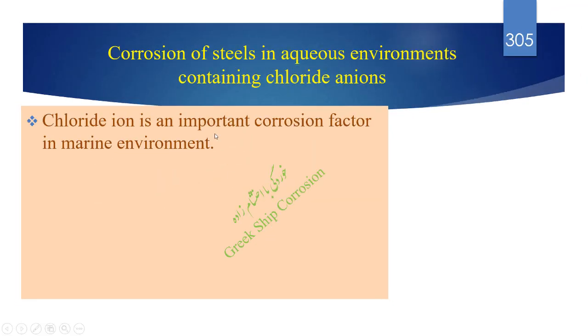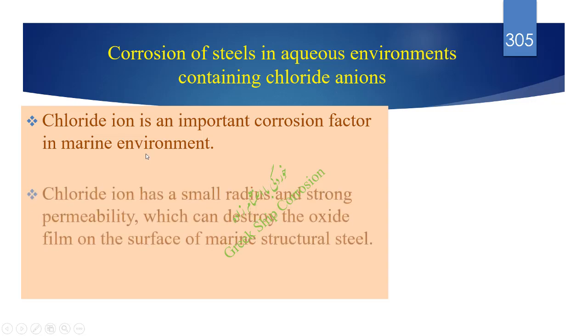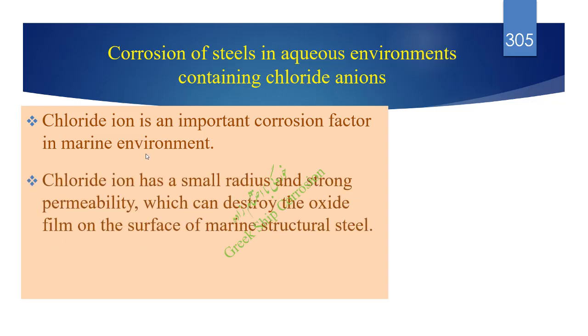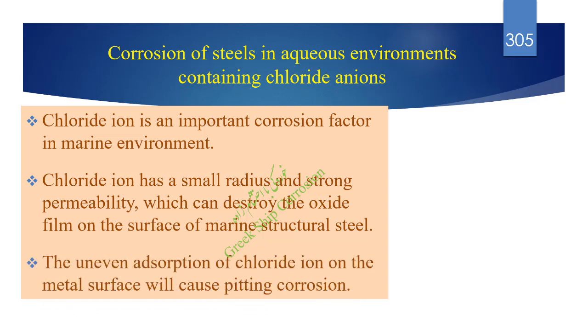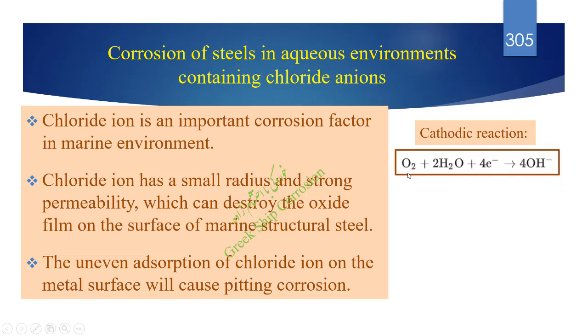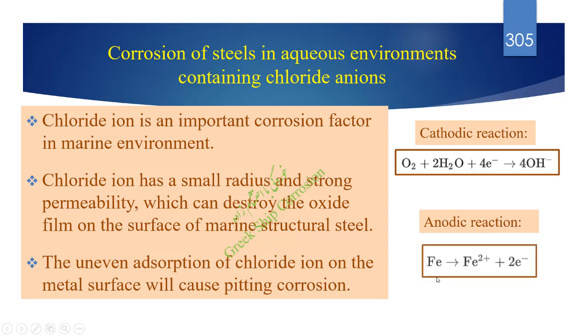Corrosion of steels in aqueous environments containing chloride ions. Chloride ion is an important corrosion factor in the marine environment. Chloride ion has a small radius and strong permeability, which can destroy the oxide film on the surface of marine structural steel. The uneven adsorption of chloride ion on the metal surface will cause pitting corrosion. In this case, the cathodic reaction is O2 + 2H2O + 4e- yields 4OH-, and the anodic reaction is Fe yields Fe2+ + 2e-.